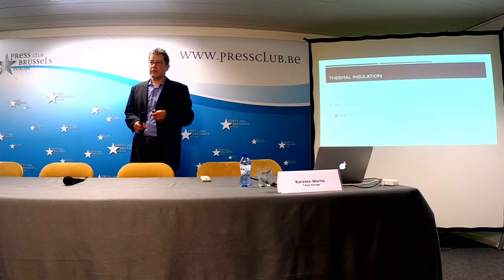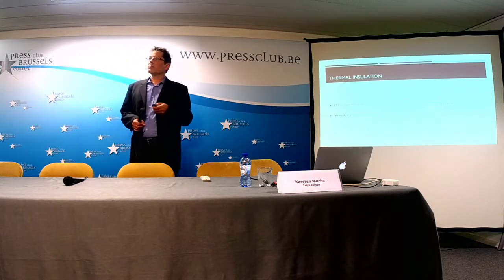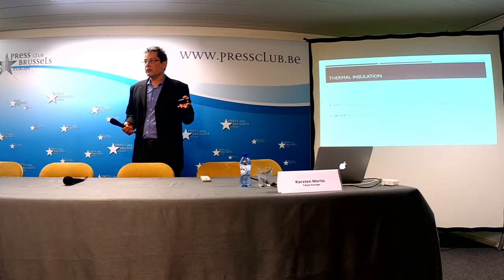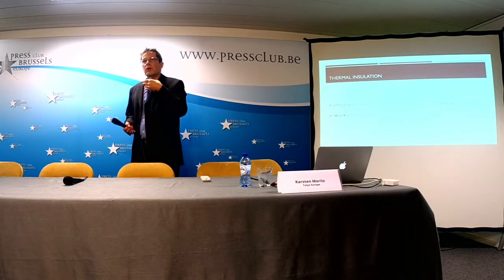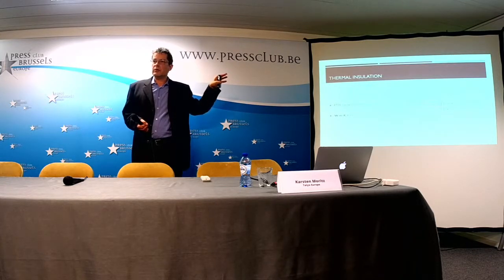U value, related to the thermal insulation: ETFE foil cushions are not as good as glass structures. Today we achieve a U value of 3.0 watt per square meter Kelvin for a double layered ETFE foil cushion, and 2.0 for a triple layer system. Meanwhile, we have also built cushions with 5 and 4 layers, and we achieve U values of 1.5, let's say 1.3 at maximum. If you compare it to glass, you get windows meanwhile with a U window value of 1.2, 1.0, and sometimes better. So this is a disadvantage at the moment, but we are giving our best to improve also the thermal properties of such structures.